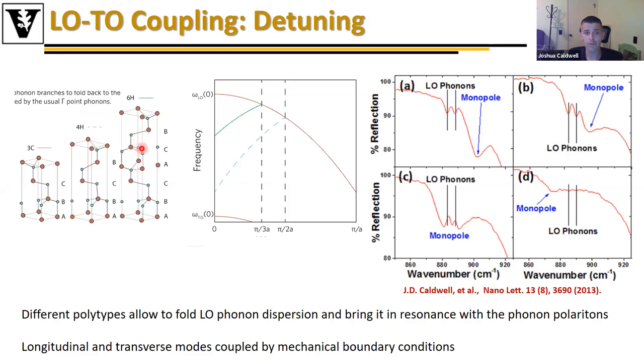6H is usually a substrate for light-emitting diodes based off III-nitride materials. And what you find is that these are not purely hexagonal. The pure hexagonal form is 2H. 4H actually has both cubic and hexagonal stacking orders, but this is more hexagonal than 6H, for instance. Now, because of that, you actually have two different unit cells, kind of like a superlattice within a two different material superlattice. And thus you end up with the dispersion of your LO phonon here, also inducing some zone folding, right?